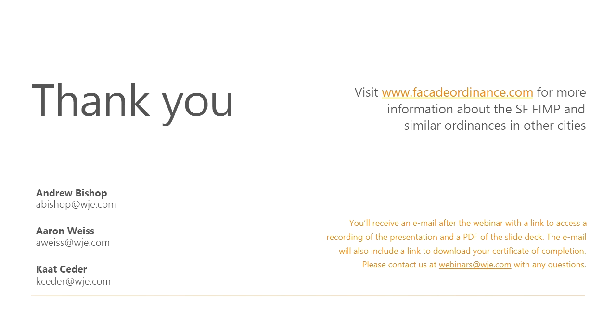Yeah, Kaat, let me know if I'm missing anything on this, but I do believe a film is better than no film, because, especially if it is mechanically fastened, you're getting a little bit of additional span resistance from mullion to mullion. It does mean if the piece does leave the opening, though, that you have a much larger piece typically that's falling as one piece. That's kind of the risk of laminated glass as well. You have a better chance of it not falling off the building, but if it does, tempered laminated glass is going to do a lot more damage than just unlaminated tempered glass. Kaat, do you have anything else on that one?